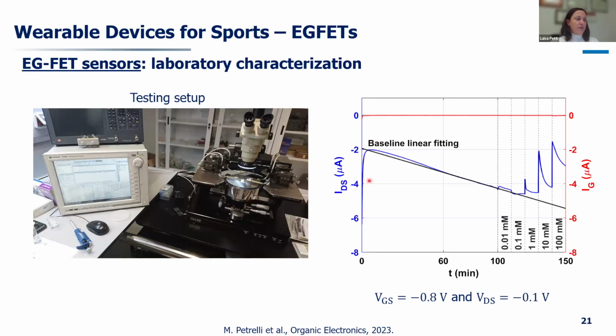What you see here is that you first have a time where you need to form the electric double layers, but then there is actually a change in the variation, which we are calculating, so doing a baseline fitting in order to remove the stabilization time, which typically takes more than an hour.